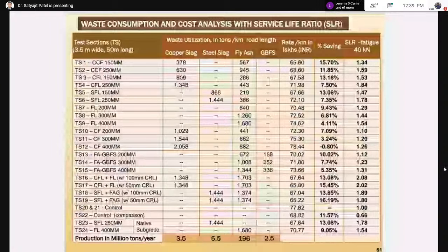Then this material is for different thickness. Like if you take copper slag fly ash, the TS12, test section 12, if you take 400 mm copper slag fly ash, in that case the cost saving will be negative because the thickness is quite high, 400. But in all the cases the service life is more than 1. That means the service life is higher than the control material, in addition to the cost saving. So by using this waste material, you will get a higher service life ratio with more cost saving. So the cost saving will be around in the range of 10 to 12% of the total cost.